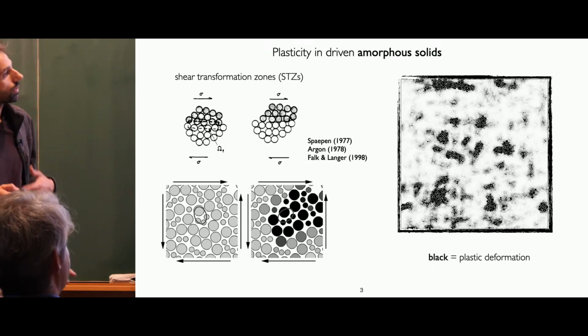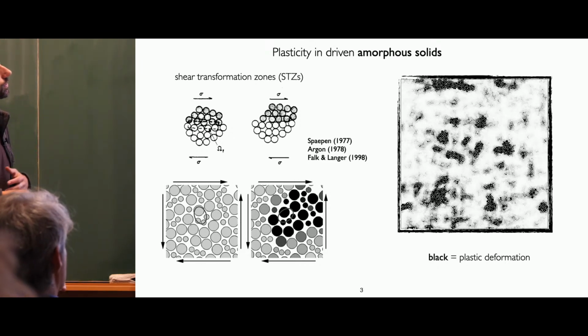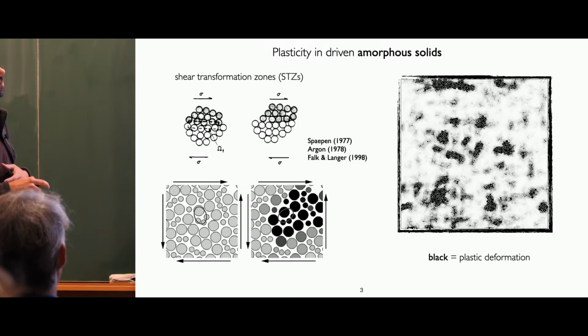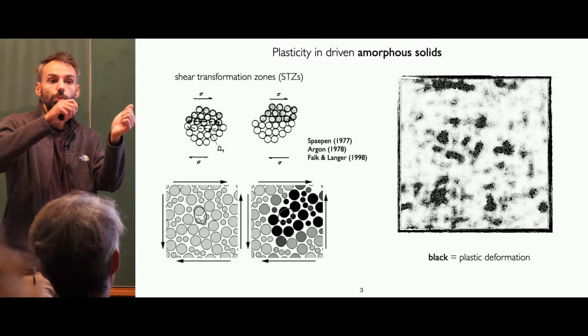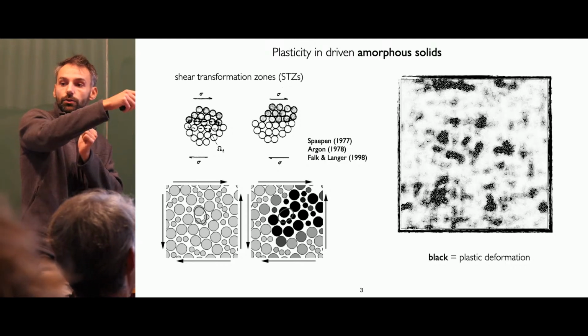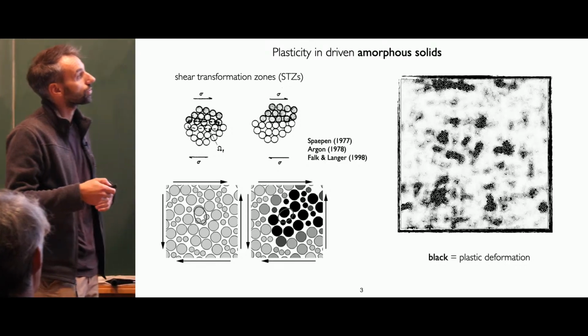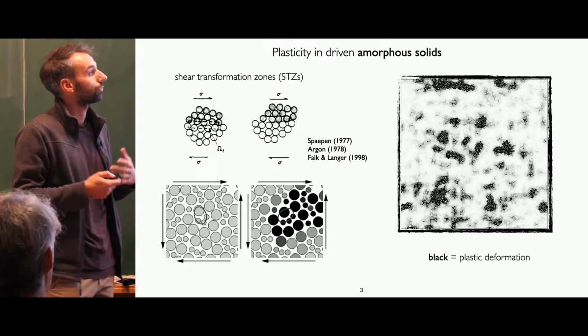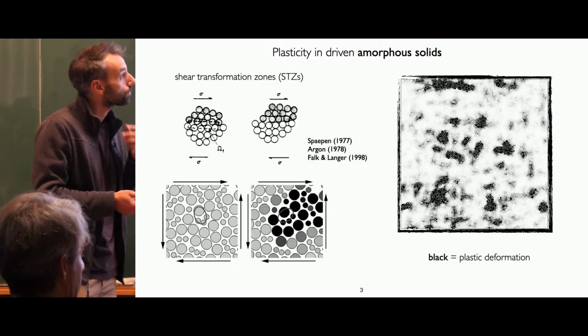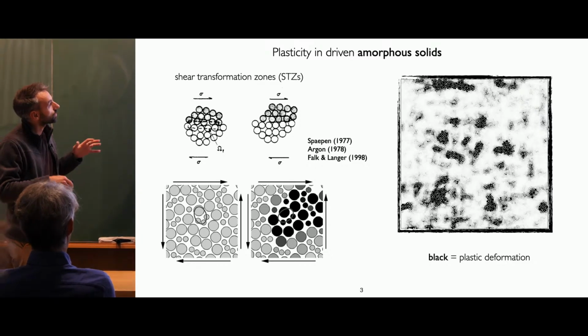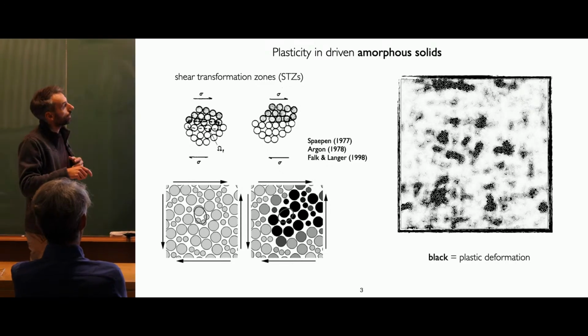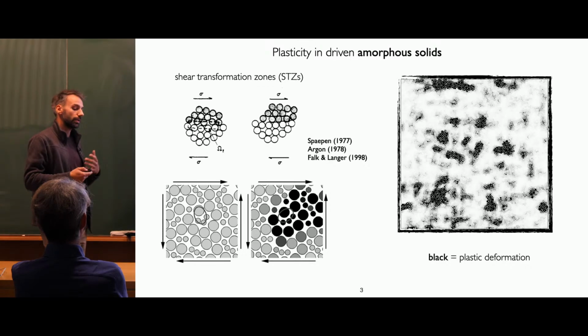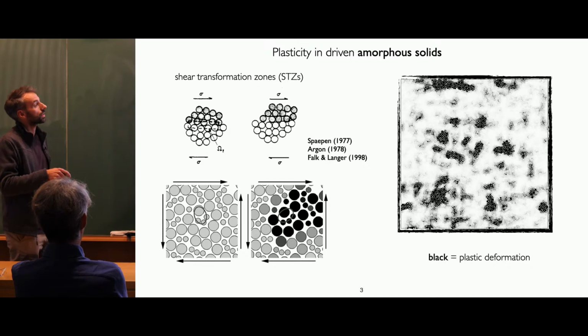So, a bit like viscous dynamics, you will have some rearrangements that in mechanics they call shear transformation zones, where when you start to shear the system locally, some particles will undergo a small shear transformation and rearrange from one state to the other. There will be some stress release across the system, and that could lead to emergent collective phenomena like avalanches or strain localizations. And the same communities that developed tools to understand patterns like locally favored or unfavored structure that lead to viscous dynamics also use these tools or develop new tools to predict plasticity in amorphous solids.